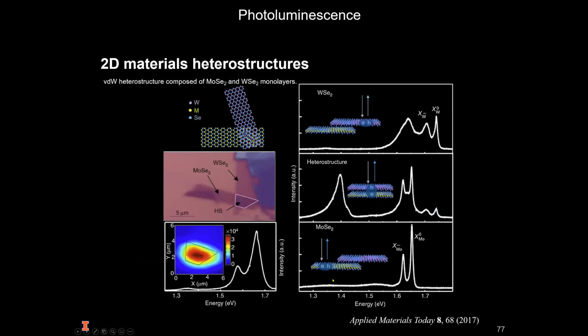Here is a work demonstrating the formation of a van der Waals heterostructure composed of molybdenum diselenide and tungsten diselenide monolayers using photoluminescence.